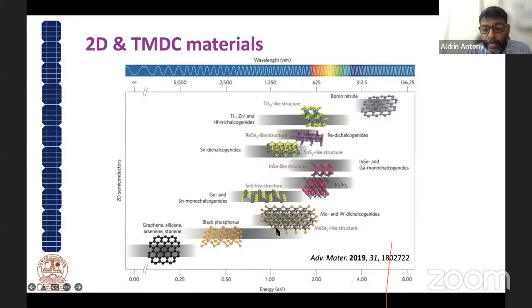And if you look into the different materials and the band gap energy, something near 1.5 gives the better materials, and you could see MoSe2 or MoS2, this type of materials works better. We call them molybdenum or tungsten-based chalcogenides, transition metal dichalcogenides, TMDC. They work with a band gap energy between 1 to 2 electron volt, and they are very ideal to be used for solar cell applications.